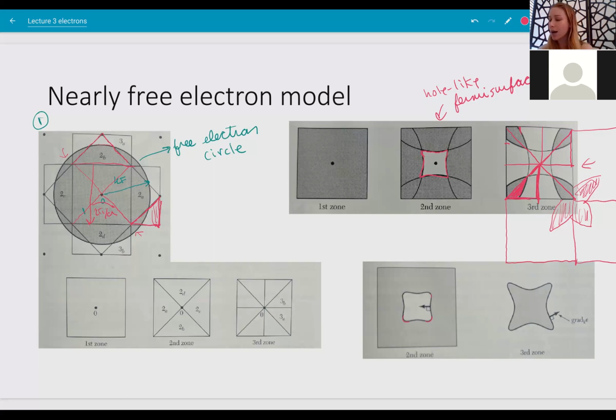And then these actual Fermi surfaces, these actual contours of constant energy, where that constant energy is the Fermi energy, end up being a different area, and they can also be a different sign of carriers. So this is an example. This illustrates how you can get hole-like carriers, and how you get a small carrier density when you thought you put in a large carrier density, just starting off with a free electron model and then introducing the lattice, making it into a nearly free electron model.